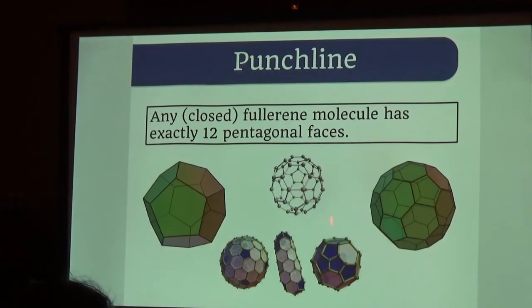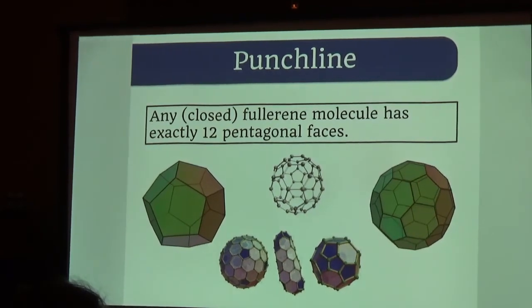It has exactly 12 pentagonal faces. And why is this relevant? Well, it means that when we synthesize nanomaterials, and in particular carbon nanomaterials, so fullerenes, we now know exactly how many pentagons we have to have. There will be no way of synthesizing nanomaterials or fullerenes without having exactly 12 pentagons.